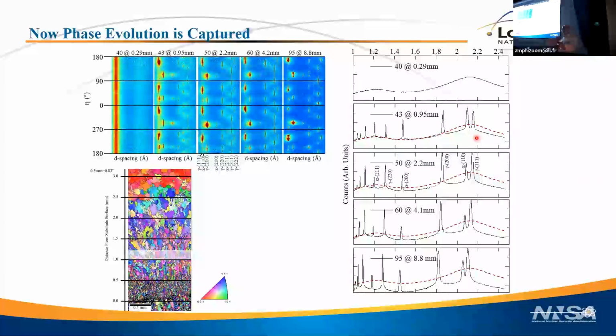In reality, I'm sampling from one surface to the inside to the other surface. So there's a gradient there, which dictates part of that mixture as well. But you can watch it evolve. You'll see that the ferrite peak here, the BCC phase of the steel, goes from being the strongest peak to the weaker, and the austenite becomes stronger. So that's the solid-solid phase transformation that you see between those two.